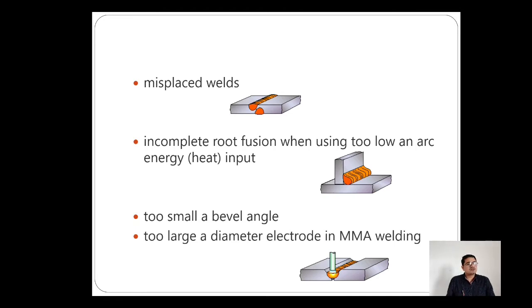The fourth one is, friends, the too small bevel angle. If you remember the last class, we discussed the bevel angle and included angle. If the bevel angle is too low, then penetration may not properly happen. The last one is too large a diameter of electrode in MMA welding. As I discussed earlier also, if we have taken less root gap, we cannot achieve proper penetration on the root. In a similar way, when we have the root gap but a higher diameter of electrode, then penetration may not properly fuse. So in those cases, the root gap will be taken on the basis of the electrode we are going to use in the root.